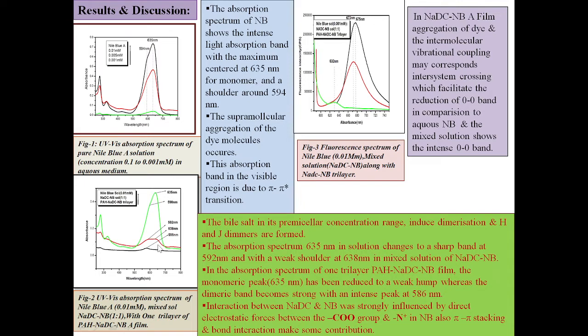The absorption band at 635 nm in solution changes to a sharp band at 592 nm with a weak shoulder at 638 nm in the mixed solution of NaDC and NB. In the absorption spectrum of one trilayer PAH NaDC NB film, the monomeric peak at 635 nm has reduced to a weak hump, whereas the dimeric band becomes strong with an intense peak at 586 nm. The interaction between NaDC and NB was strongly influenced by direct electrostatic forces between the COO minus group and the N plus in NB; pi-pi stacking and hydrogen bond interaction also make some contribution.